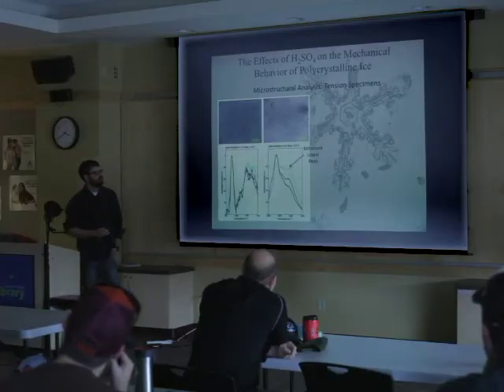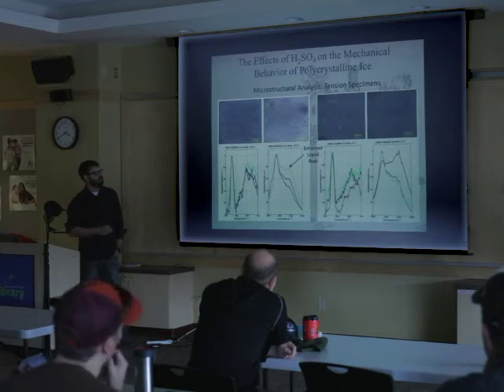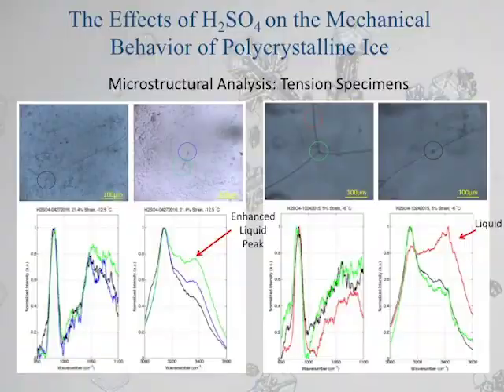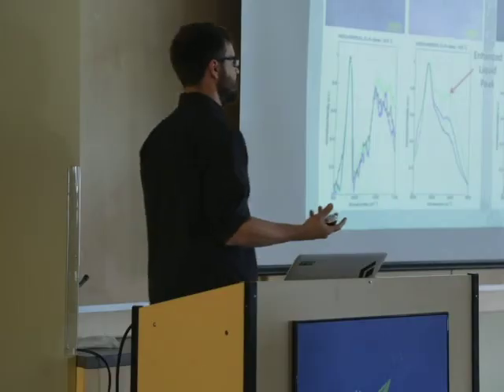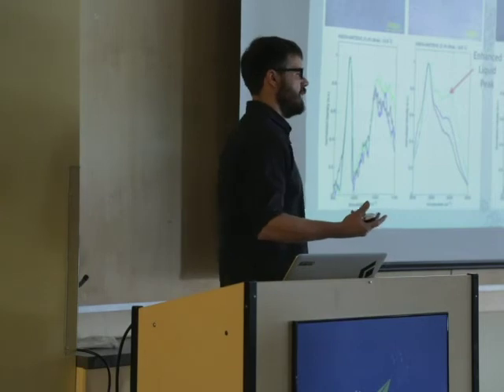And what we saw from another sample was that, again, we have the sulfate peaks here, but we actually did see a liquid peak sometimes. This is at a grain boundary in between the two pieces of ice. So what this means is that what you're really dealing with is this molten system. It's not just solid ice that you're dealing with.